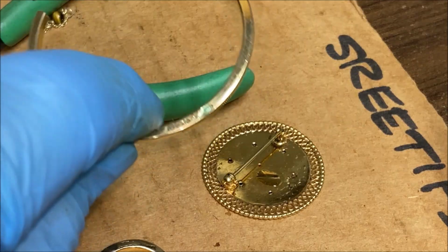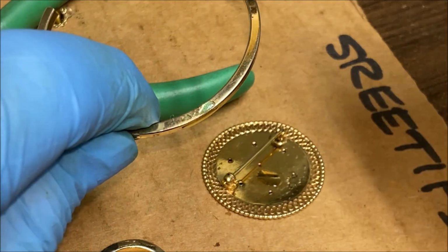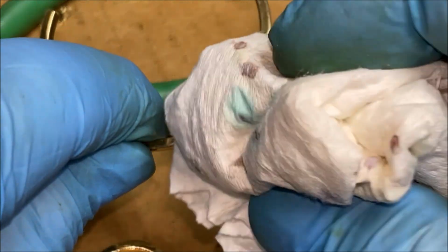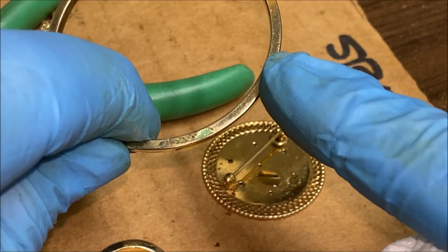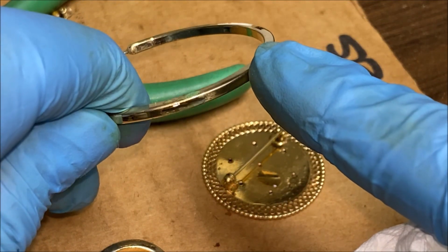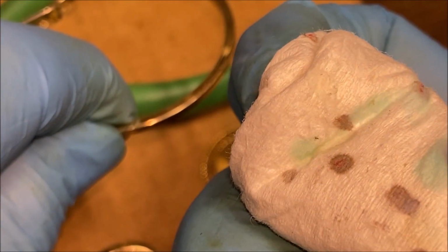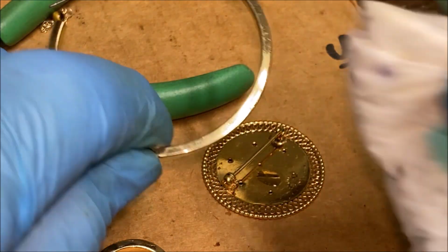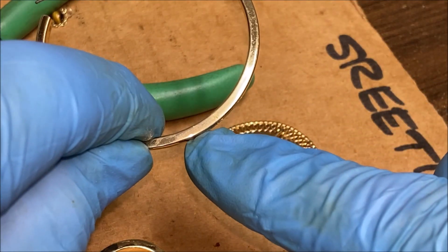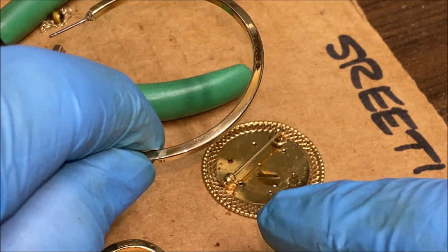Here's a piece that I put on there about a minute ago or so, maybe two now. So this has got a thicker coating of gold plating on it. It hasn't eaten through as quickly, but it's still turning green on my cloth, which tells me that the acid is getting through to the base metal underneath.